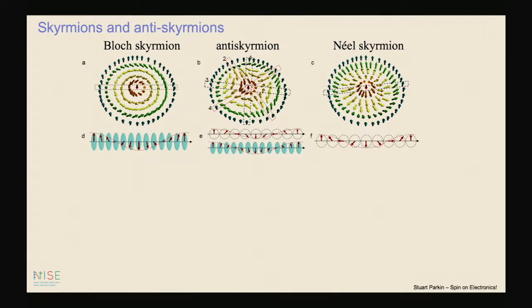So on the left-hand side you can see a Bloch skyrmion. In this case, the wall surrounding this reversed region of magnetization is a Bloch wall. And I think you can see in this cartoon that means that the moments in the wall itself will be oriented tangentially to the circumference of this typically circular object. On the right-hand side, you can see a Néel skyrmion. And in this case, the magnetization in the middle of the wall is oriented along the radius. I think you can see that in these two cartoons.